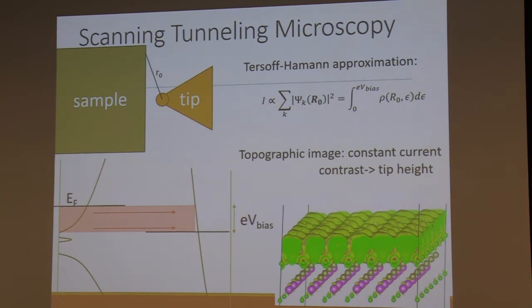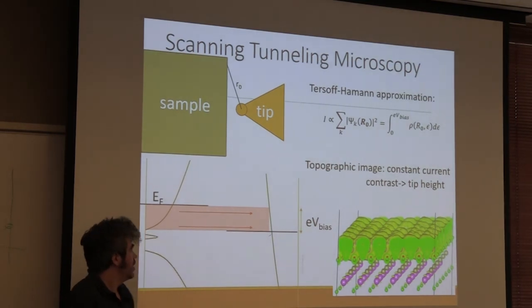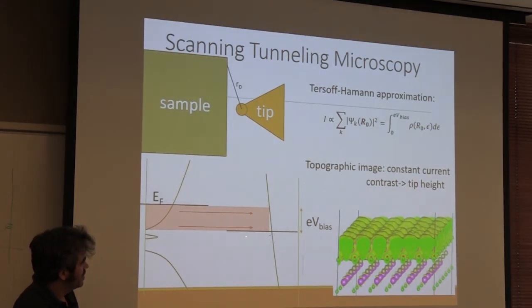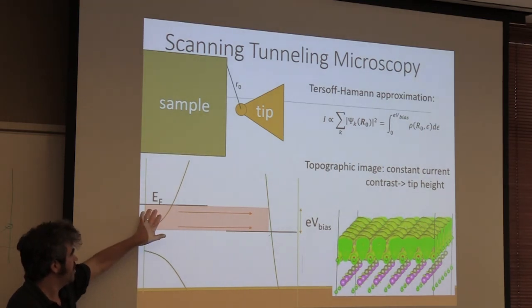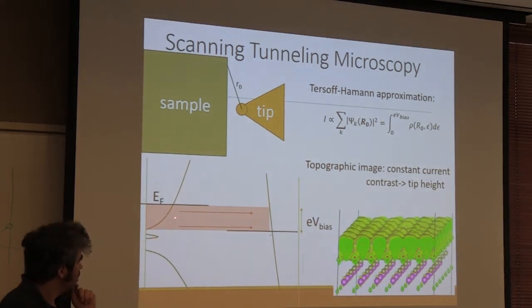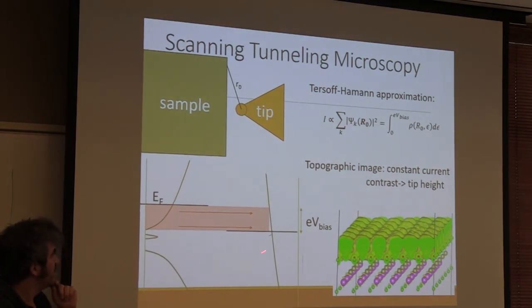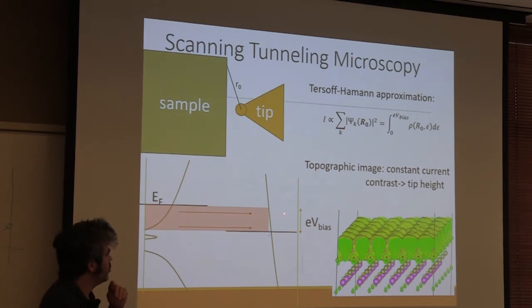So when they do STM, they apply a bias. Essentially, what they're doing is making there be a difference between the Fermi level in the sample and in the tip. Right, so this is the Fermi level in the metal tip, and this is the Fermi level in the sample. What that allows is that all of these states in the sample now have states they can tunnel to in the tip. Right, so this tunneling probability, or the current really, you can use the Tersoff-Hamann approximation, and if you assume that it's an s-wave process, you can